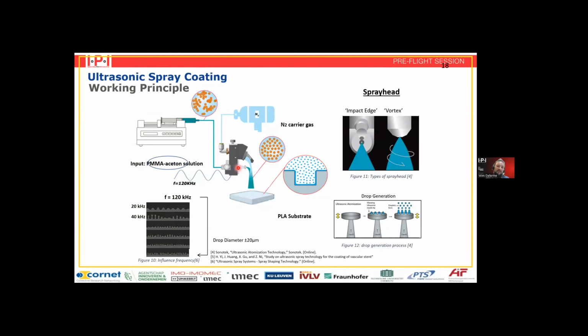your ink formulation towards the nozzle plate here, and this nozzle plate that you can see here on the right bottom side, on this nozzle plate, you apply your ink. And by ultrasonically vibrating this ink, you create standing waves and droplets that are generated from these standing waves. And these droplets contain the solvent with the functional material in it, and is brought towards the substrate by using a carrier gas. In our case, we use nitrogen, but this can also be something else.